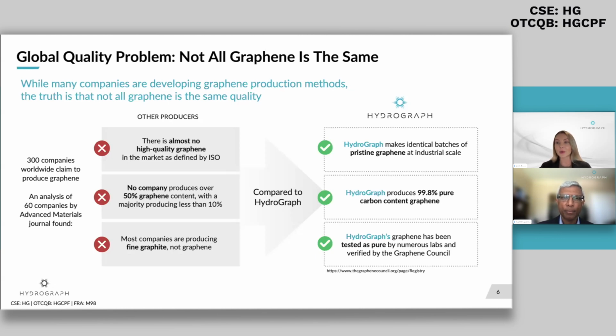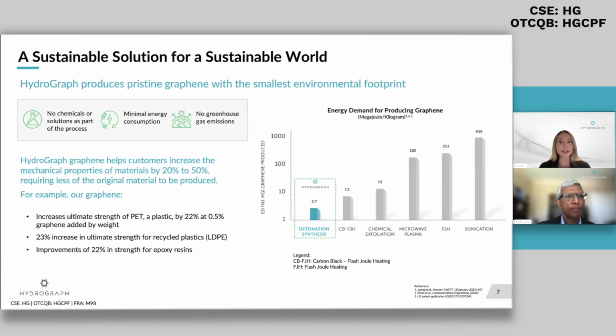We have a very different production process, and because of that, we have a very pristine material. So we make identical batches because we're synthetic. Every time we turn on the reactor, it is exactly the same thing. We produce 99.8% pure carbon content graphene, and this has been verified by numerous labs and verified by the Graphene Council. To go further into this, we produce pristine graphene with the smallest environmental footprint. Our production process is unique. Our energy demand is unique, and our end material is extremely unique.